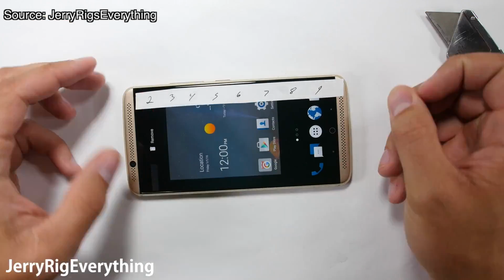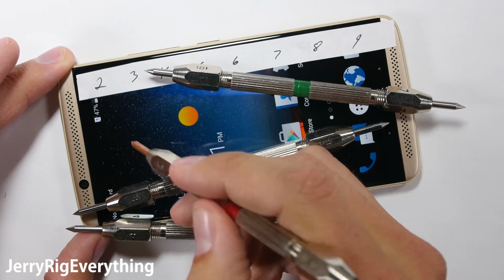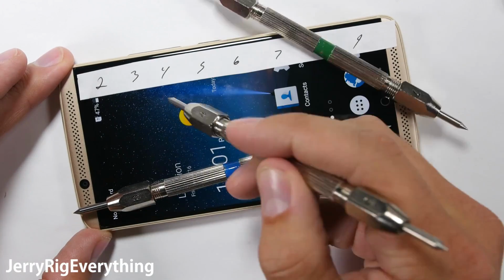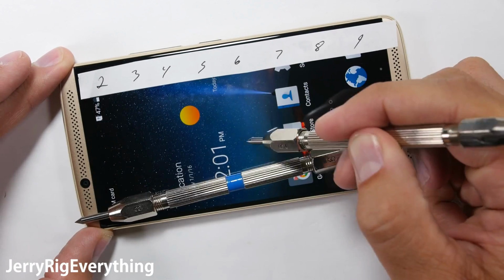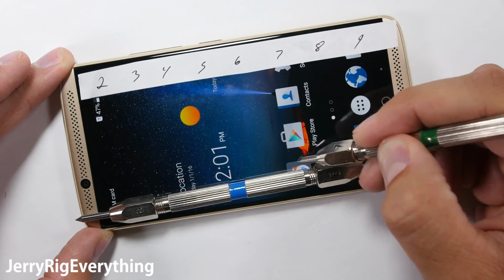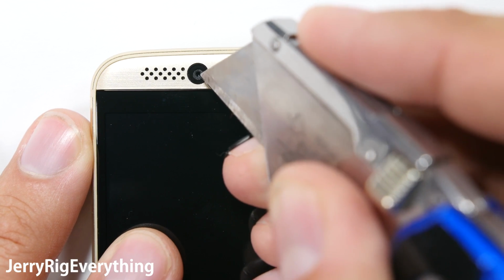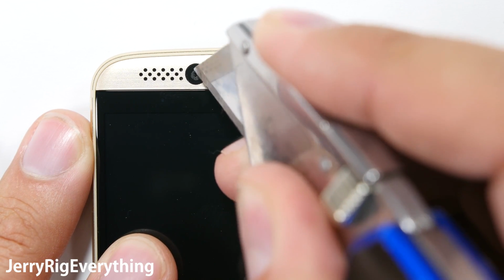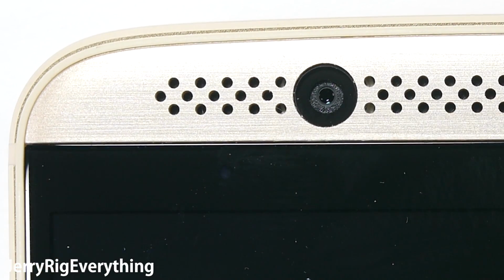It's a good point, but we did argue this. We made the point that Zach has performed this test over 30 times, and that even outside a laboratory setting, there must be at least some degree of consistency in his approach and execution. But they pretty much shut that point down with this, and I quote: "The hardness pick that was used in the video is a 3. That's softer than the glass material itself. Oftentimes when you have a softer material, and depending on what load you've used, you tend to see material transfer on the test substrate. Material transfer on the test substrate is not necessarily a scratch, but it can appear as a scratch to the untrained eye."